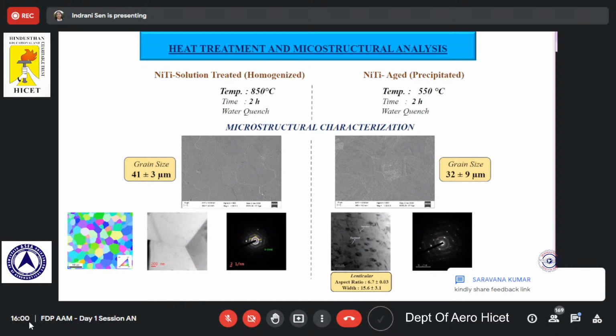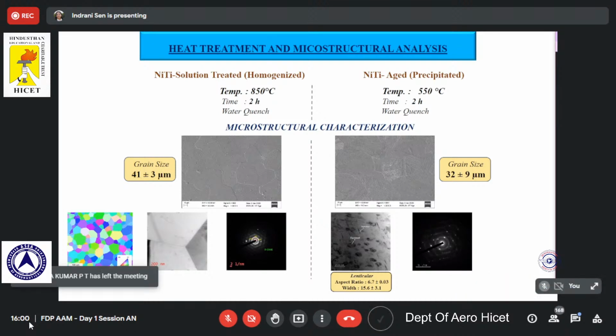Martensite in general is brittle. Martensite is helpful to SMA. What you're talking about, maybe that is the martensite of steel. Here, martensite is the terminology. Martensite is used, but the crystal structure and properties of the shape memory alloy martensite are completely different from those of steel. It is called martensite because it undergoes a diffusionless transformation from austenite. As per the nomenclature, anything which is undergoing diffusionless transformation, we can term as martensite. So it is not about helpful or anything. Conversion of austenite to martensite is not the only factor of SMA. The main part is converting it back. It is the reversible transformation that makes shape memory alloy recover its shape, which steel or iron-based systems cannot.